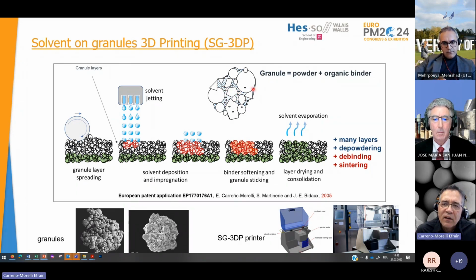The idea is to make a spheroid-shaped granule, which is easy to spread in a layer, and because you already have the binder between these particles, what is possible is just to drop a solvent. The solvent, which can be water-based, alcohol-based, any solvent compatible with the print head, can be used to soften the polymer in the granules and to paste the granules to each other. In this way, we grow layer by layer a green part, and after depowdering, we can debind and sinter.